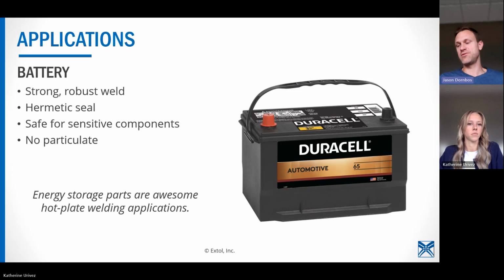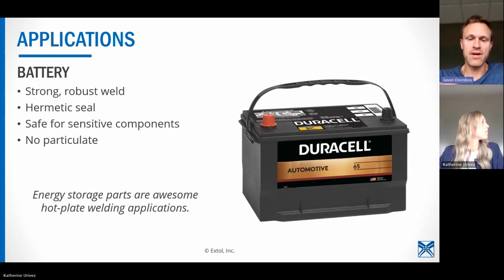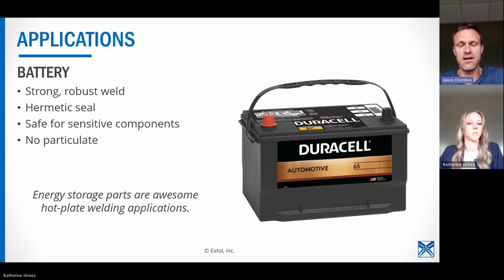It's okay because you fill the battery and then you weld this lid on. And that can often be automated, whether you're having a robot feed it or maybe parts are coming in and going through the side of a hot plate welder. You get strong, robust welds. You need it to be hermetically sealed. There's sensitive components inside of the battery, and those are kept safe from the hot plate process. And there's no particulate. So energy storage and battery applications are great for hot plate welding.